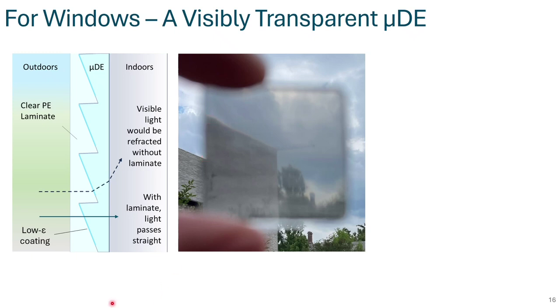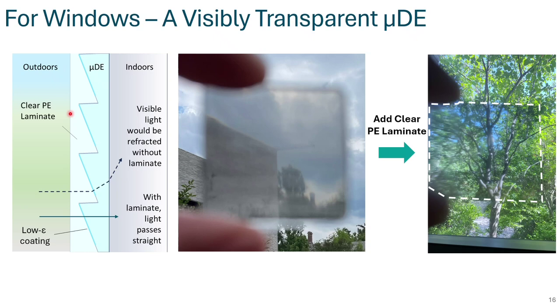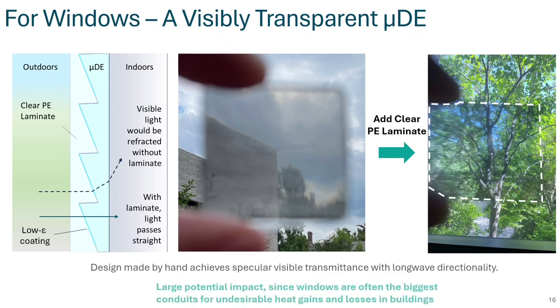To solve this, we simply laminate a polyethylene film on top of the pattern to fill it so that it effectively makes the structure into a planar solid film and then restore the image that was previously distorted. You now see a transmission well aligned with the background. This variant is still at the stage of proof of concept, but presents strong potential as windows or major conduits of heat leakages in buildings.